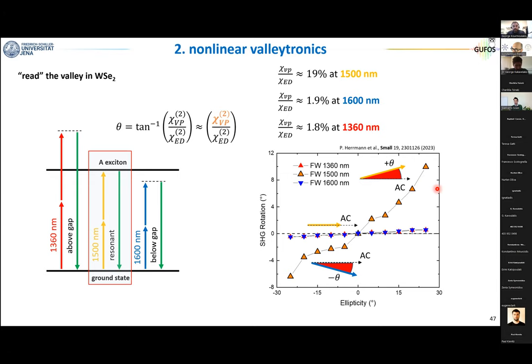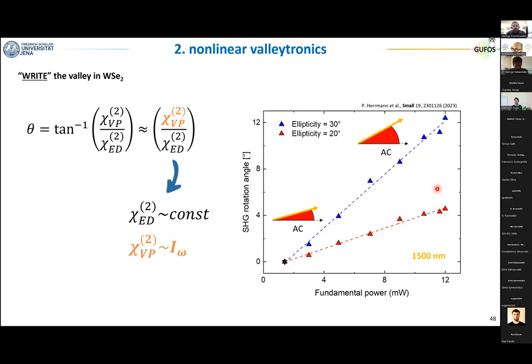Okay, so this is a very powerful method, and there is one additional element that I want to mention, and then in the last 5 minutes, I will try to tell why this is important. And it's the fact that while the electric dipole response, so the nonlinearity coming from broken space inversion symmetry, is constant with power, it's an intrinsic property of the material, the one coming from broken time reversal symmetry is a function of the power. And this is because we break time reversal symmetry, so we generate the valley imbalance with the same pulse that we use to read the valley imbalance.